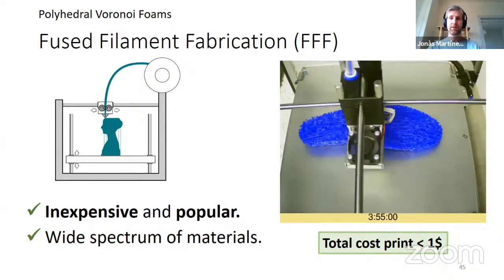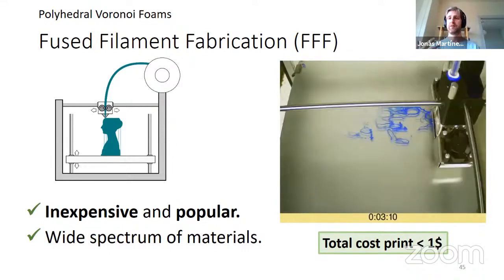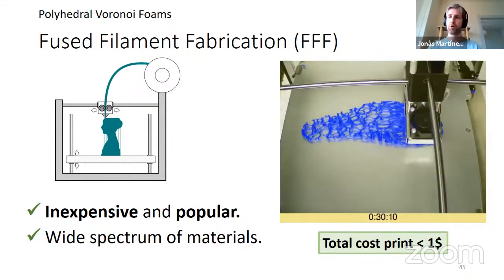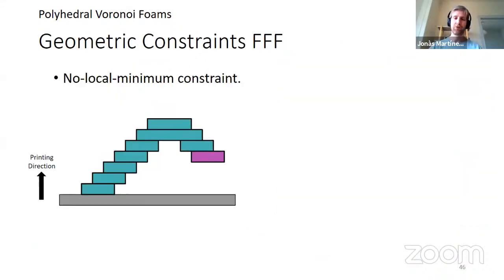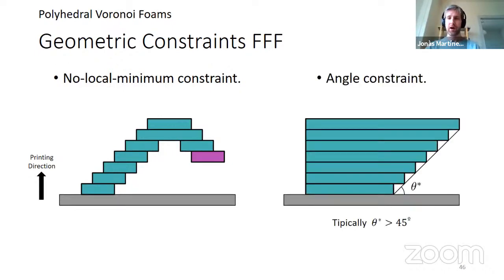So it's a very nice fabrication technique that is inexpensive, but on the contrary, it imposes constraints on the fabrication that are pretty strict. The first one is, again, the no local minimum constraint. You cannot deposit filament anywhere. There's some overhang angle that you need, and typically this overhang angle is bounded. So basically, if you exceed some angle, it will fall apart. So you have a safety angle, let's say, where you can deposit the filament such that it remains self-supported.